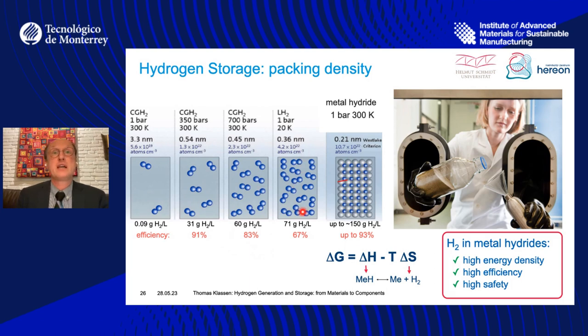Or you can liquidify hydrogen, then that's physically the highest density here. With cooling down, you lose about 33% of your energy. And what we actually propose here is to use metal hydrides. That is, we split the hydrogen molecule, and the hydrogen then diffuses into the interstitial sites of metal and forms a chemical bond to the metal.